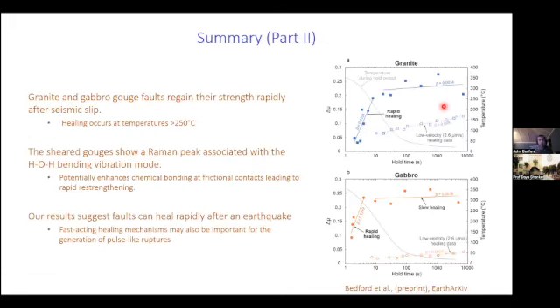But regardless of what the healing mechanism is, the summary of this part of the talk is that we see this rapid healing immediately after a high velocity slip event. This rapid healing occurs while the gouge is still hot, and we find evidence of a chemical change associated with the materials that have been sheared at high velocity, which is potentially suggesting that it's chemical effects that are causing rapid healing on these gouge faults. And our results suggest that if faults can heal rapidly after an earthquake, and they may also, if the healing mechanisms become more efficient as the fault is more localized, or under higher stress conditions, they could also be important maybe during rupture propagation for the creation of potentially pulse-like ruptures.